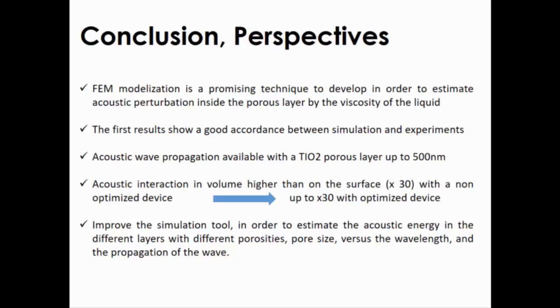As conclusion, I can say that the modelization by finite element method is a good technique in order to take into account the physical parameters of the porous layer. It's difficult to do it analytically. The most important parameters are the pore size, the porosity, and the thickness of the layer, but many other parameters which are difficult to estimate, we can take them into account. We have obtained good agreement between experiment and simulation, and we can increase significantly the sensitivity of the device versus viscous damping. Our future work will be to improve the simulation tool in order to estimate and to optimize the device and to trap more acoustic energy as possible in the sensitive layer. Thank you for your attention.